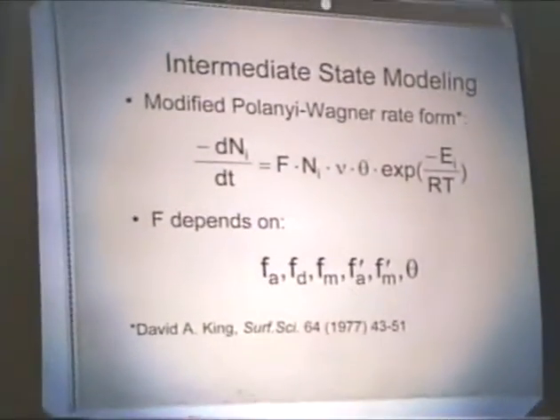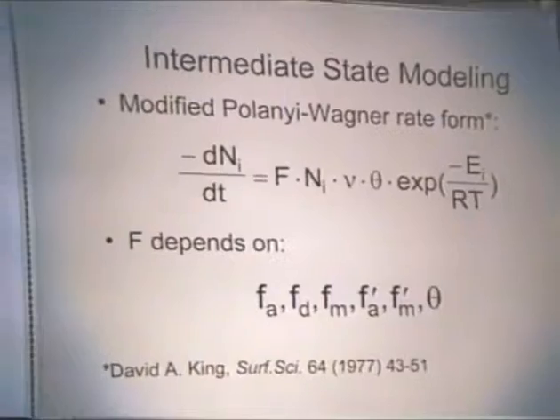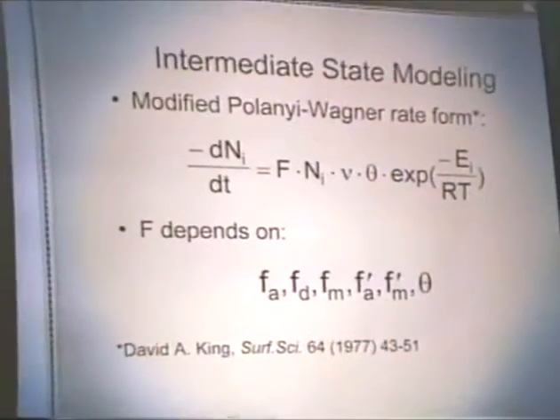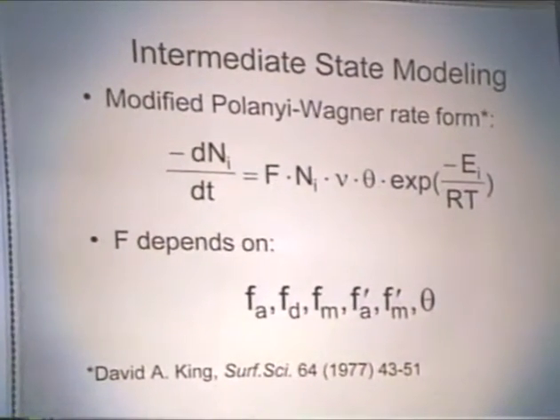The second possibility that I mentioned is desorption through a precursor state or intermediate state. This case has some appeal to us because this type of behavior was observed by King and co-workers in the mid-70s for molecularly adsorbed CO on platinum. And in light of the fact that the carbides and nitrides are known to possess catalytic properties similar to platinum, this is an appealing idea if we're able to formulate it to match our experimental results.